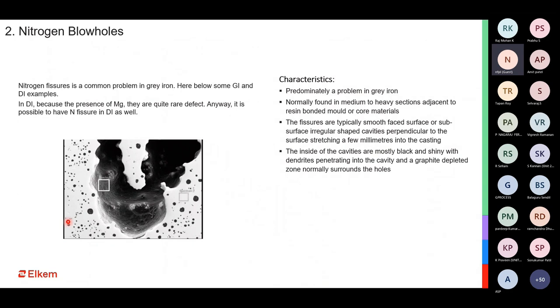Nitrogen blowhole. In gray iron, nitrogen blowhole or nitrogen fissure is a very common defect, but in ductile iron it is quite rare. Why is it rare? Because you have the presence of magnesium, and in the presence of magnesium, nitrogen fissure or nitrogen defect normally does not happen. But it cannot be completely ruled out. You also have some rare occasions when nitrogen defects come into ductile iron castings as well. How do you resolve it?